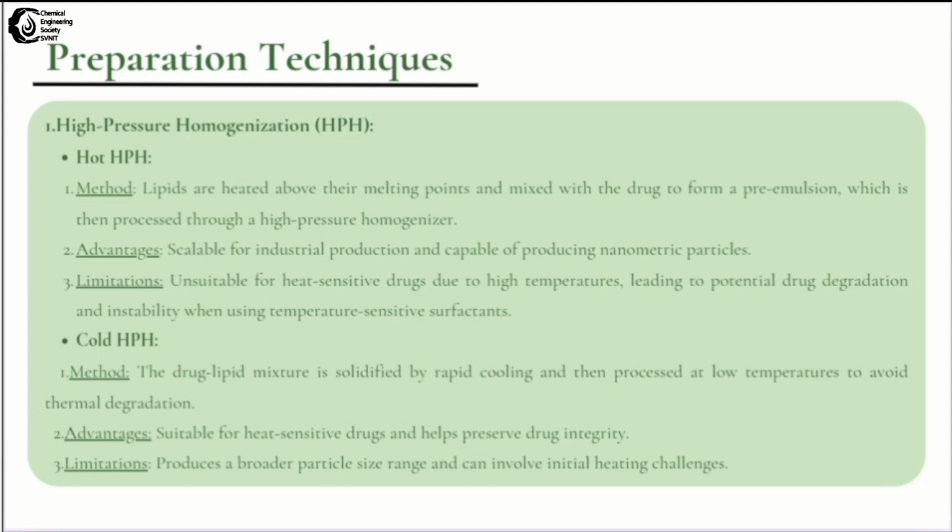The advantage of using this technique is that it can be used for large scale production like in industries. And coming to the limitation, it is not suitable for heat sensitive drugs as it can lead to drug degradation and instability. Now, cold HPH, in this method, the drug lipid mixture is solidified by rapid cooling and then processed at low temperatures to avoid thermal degradation. It is suitable for heat sensitive drugs, but the limitation is that it produces a broader particle size range.